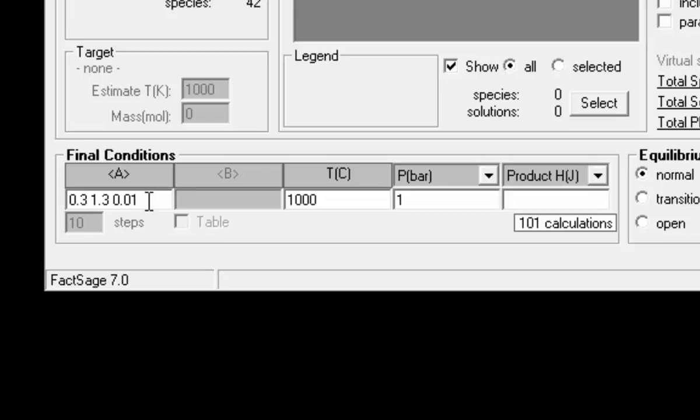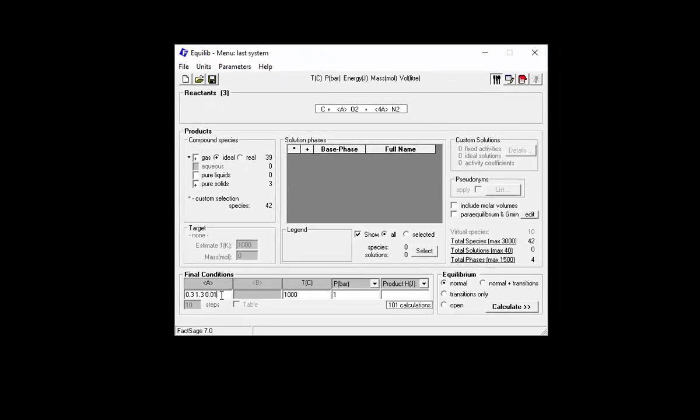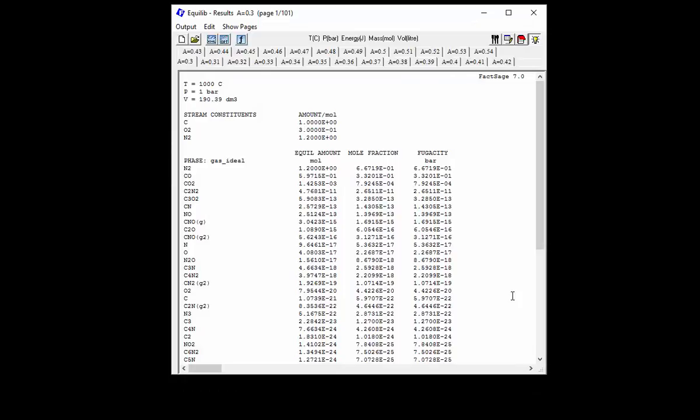As a reminder, an oxygen to coal ratio of 0.5 is needed theoretically to form carbon monoxide, while a value of 1 theoretically leads to formation of carbon dioxide. With the current setting, we therefore mimic combustion under extremely oxygen poor and extremely oxygen rich conditions. Then we start the calculation. We are not interested in the single calculation results, but want to obtain an overview by plotting the activity of oxygen, which is equal to the partial pressure, as a function of oxygen to coal ratio.